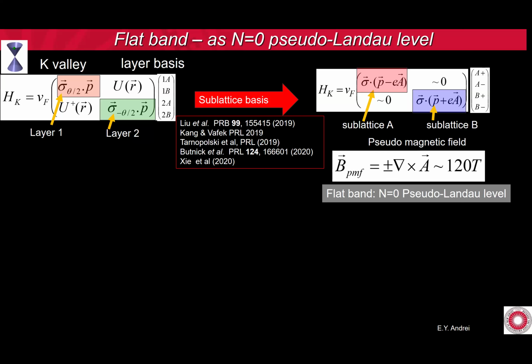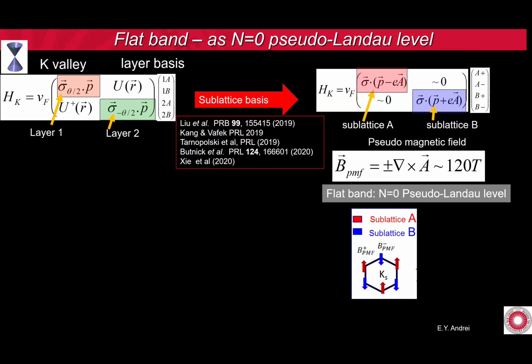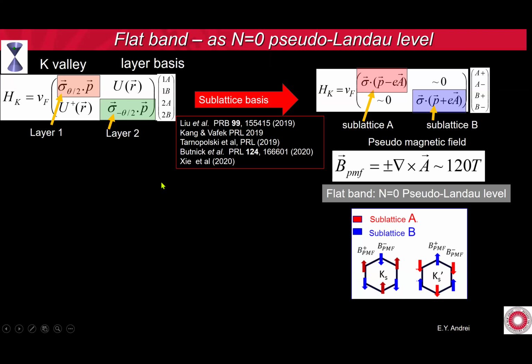And so you see immediately that this looks like an n equals 0 Landau level, but you have opposite fields in the two sublattices. So I can draw it like this. I'm sitting in the K valley, and you see that on the A sublattice, which are the red arrows here, the pseudomagnetic field points up, and on the B sublattice, the pseudomagnetic field points down. Okay. And if you do that in the K prime valley, it's all reversed by time reversal symmetry. So in the K prime valley, the A sublattice pseudomagnetic field points down, and the B sublattice points up.